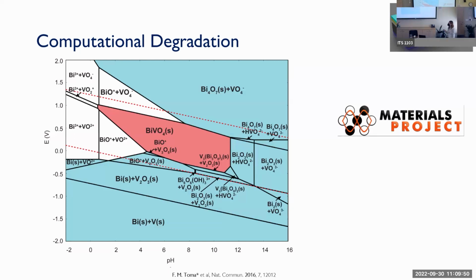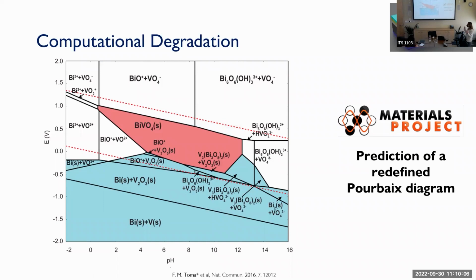So what should happen to the material, though, is that you should have a bismuth oxide layer that is solid, that should form on top of the material. But this is not what we were observing. We were observing something different, that the material was transforming and eventually leaving the substrate. So we told this to the Materials Project people, and we told them, look, your bismuth oxide is actually not forming. I'm not sure what's going on here, but there is something different going on. So they were able to prevent the formation of that bismuth oxide phase and to let the system relax, basically, and see what other phases could form under the same conditions. And they came up with this bismuth oxide hydroxide ion that is soluble and can go into solution.